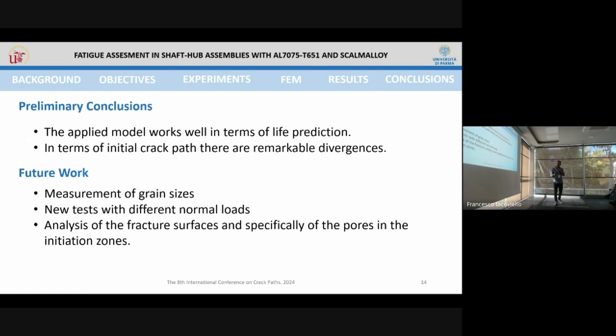We have to measure the grain size, and probably these results will vary slightly. We want to do new tests with different normal loads because all of them have been done with the same load. Of course, and this is mandatory, we want to analyze the fracture surfaces of the Scalmalloy specimens because we know that voids can modify the total life and so on.